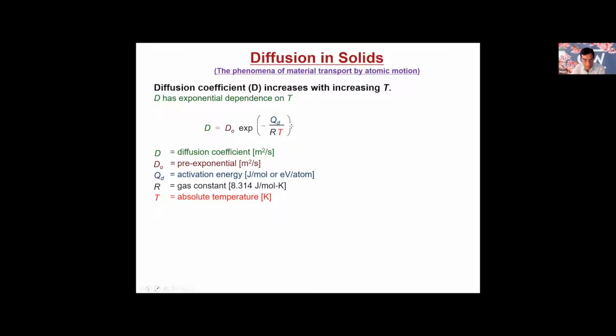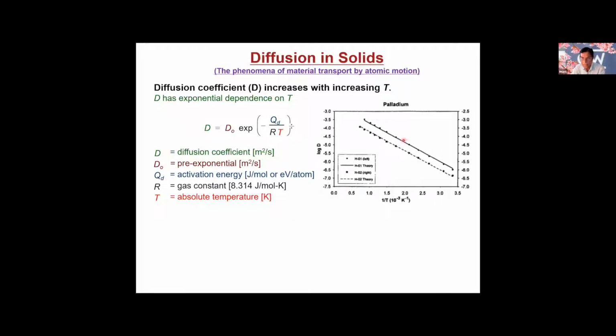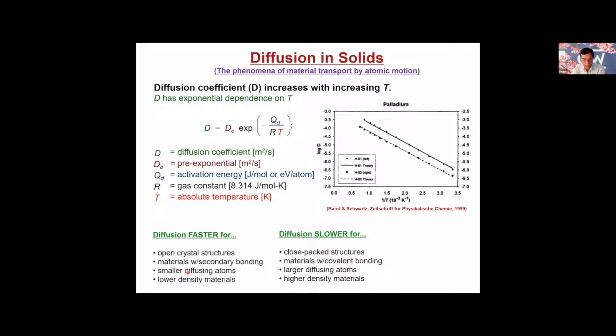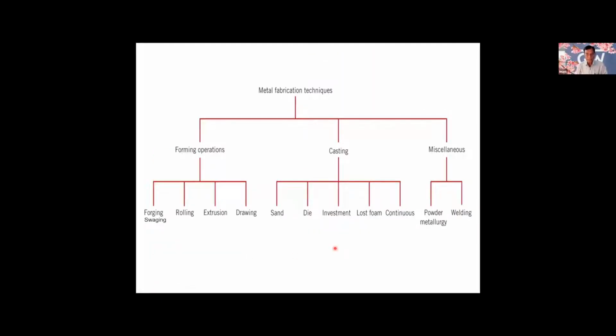And if you look at some of the results here, you have hydrogen, and this is for deuterium. This is 1 over T, and this is the diffusion coefficient. So just giving you a rough idea where the diffusion will be faster and slower. If the structure is open, it will be faster. Materials with secondary bonding, smaller diffusing atoms, and low density make diffusion faster, and the opposite of that will make diffusion slower.